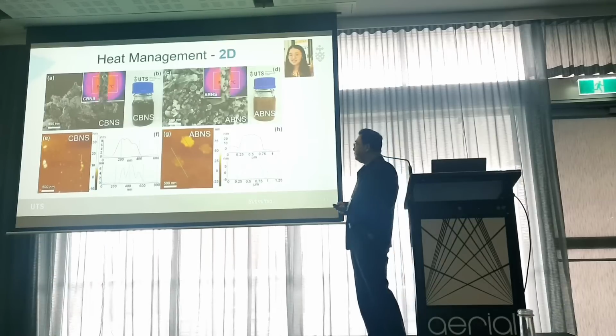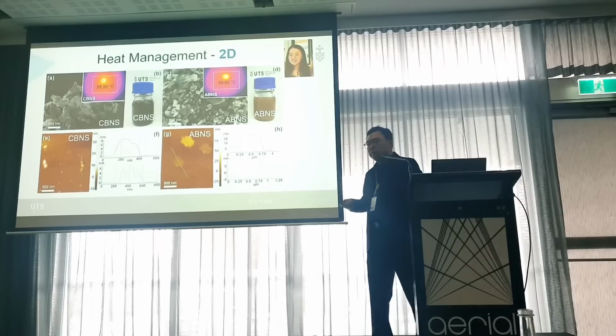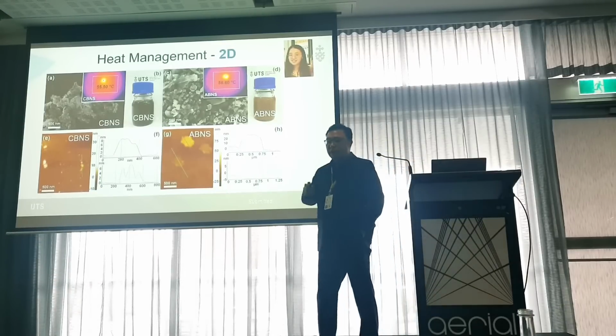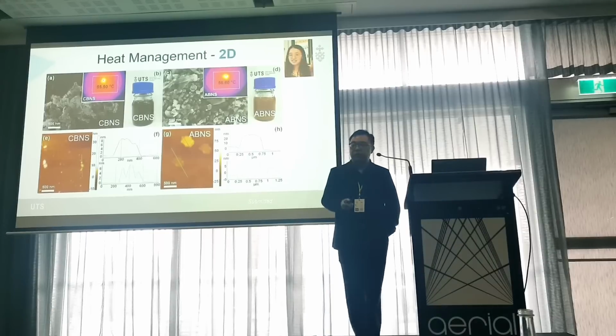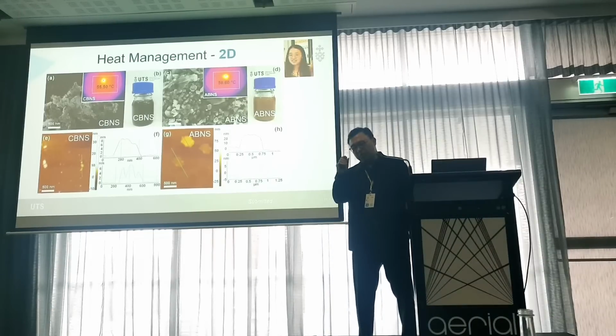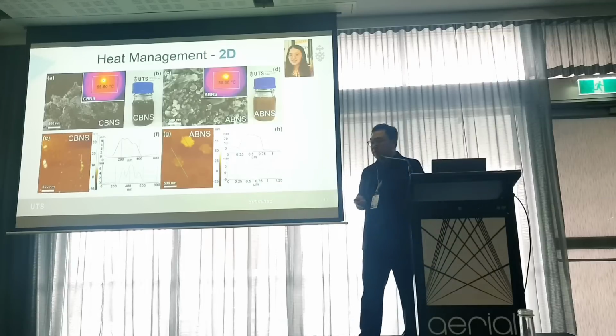We also test the photothermal performance of these materials. Under the same 10 minutes of solar irradiation, both materials achieve almost the same photothermal performance, achieving about 56 degrees centigrade in 10 minutes.